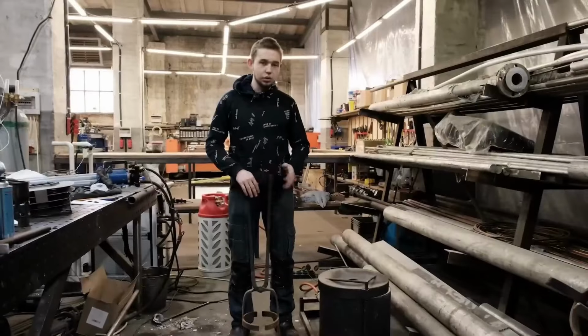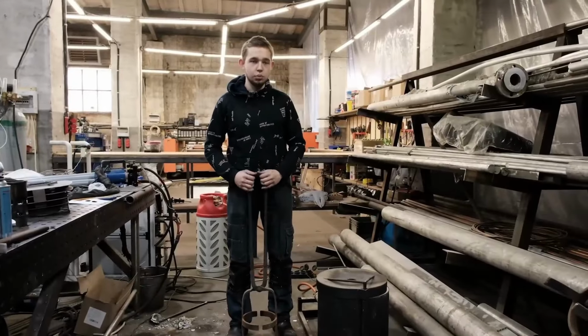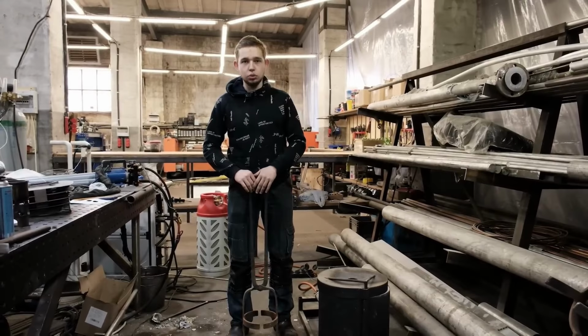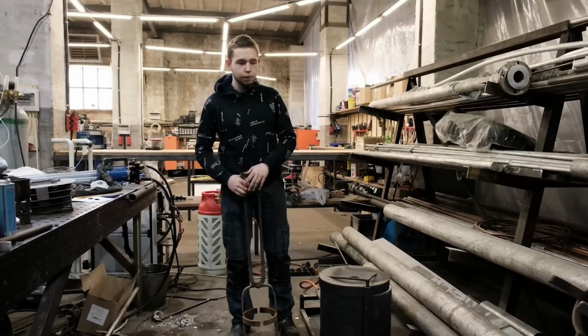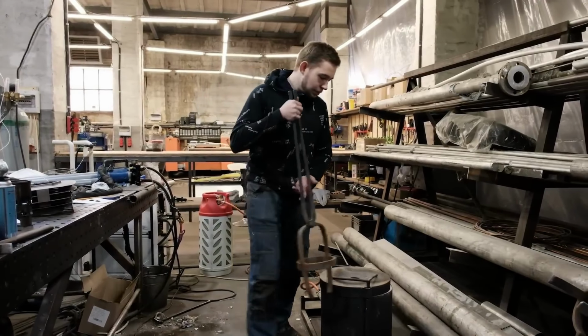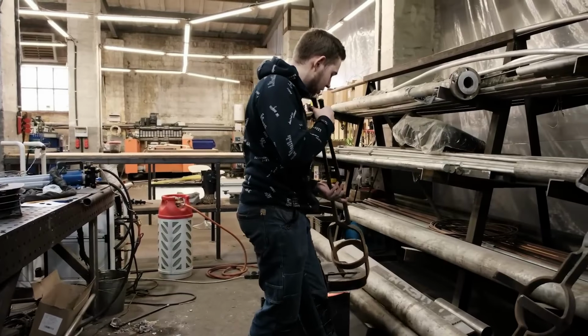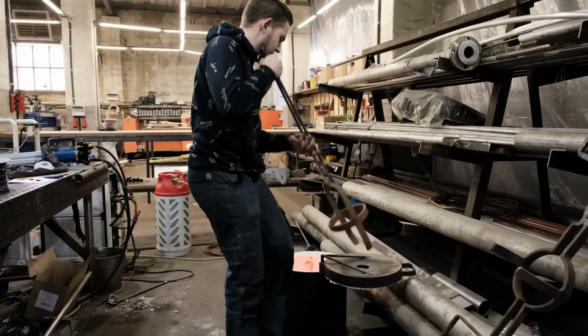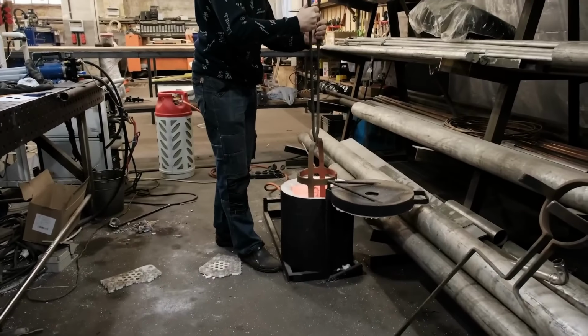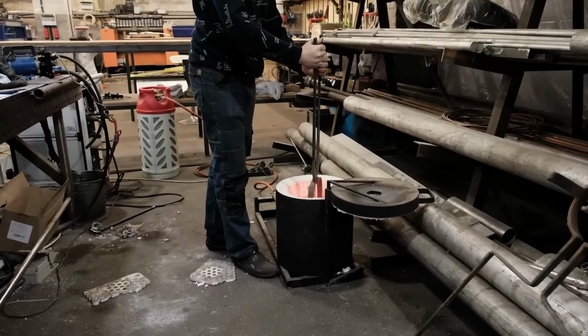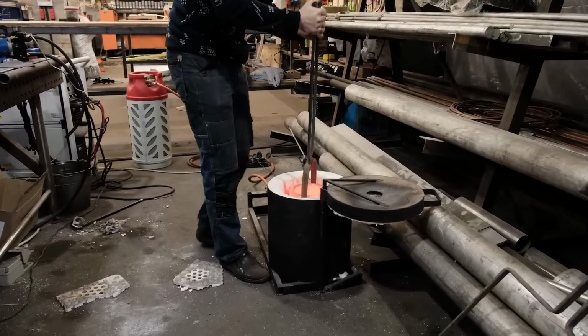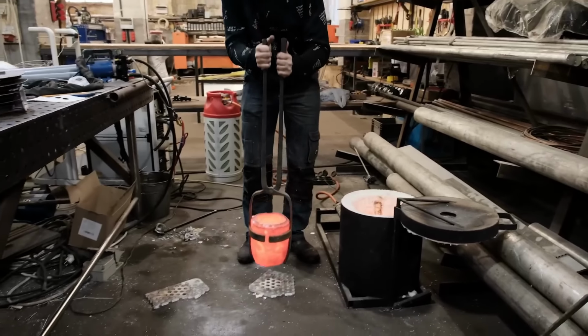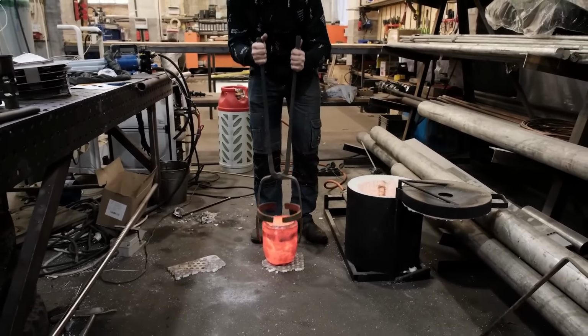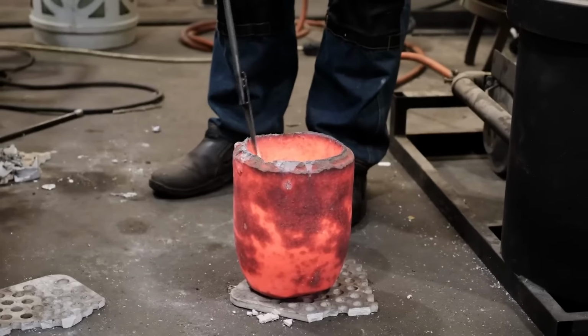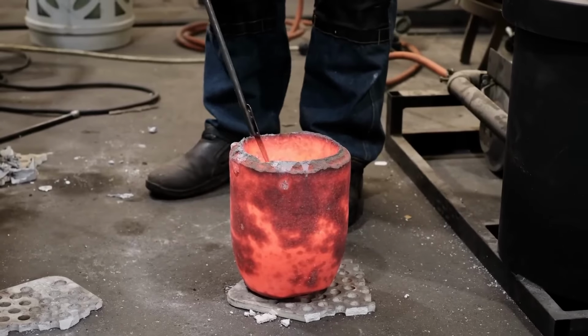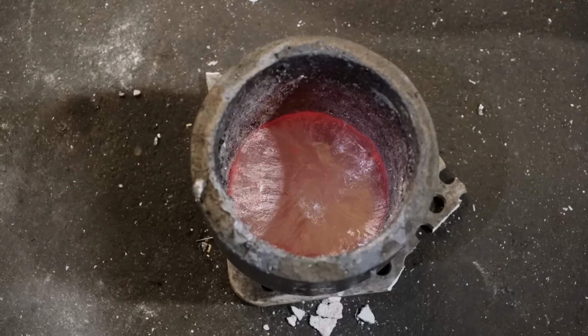Now, we take out the crucible with the molten aluminum and wait for the aluminum to cool down to casting temperature. It shouldn't be red. Now we remove the slag. We have remnants from previous attempts at making a ceramic mold. There's also various other slag.